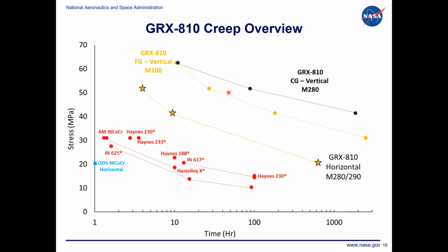What's also interesting is that we did see an improvement in the creep properties when we started printing GRX-810 in the larger 3D printers. So this is comparing GRX-810 printed in the M280, this black curve in the vertical orientation, and then GRX-810 in the M100. And really what this difference is, is that our grain structure in the M280 is coarser. The larger laser spot size produced a coarser grain structure, and that was more optimal for creep. Looking at this, at 40 megapascals in the vertical orientation in the M280, we're getting life almost to 1,800 hours. And again, this is basically above the stress that you could use any of these conventional alloys with.